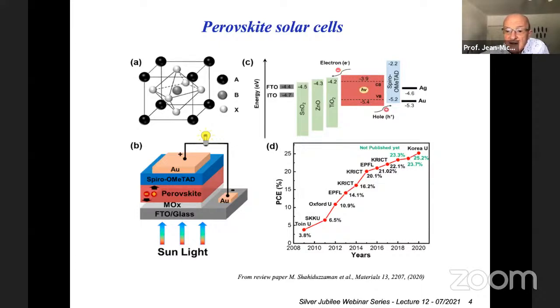These hybrid halide perovskites have been developed for photovoltaic applications more than 10 years ago, in 2009 in Japan, and very quickly the power efficiency has been ramping up to 25%, which is very close to the maximum efficiency of silicon solar cells, which is in the range of 27%, so a couple of percent below still. And the power of these perovskites is still ramping up. But there is a lot of work to do on these.